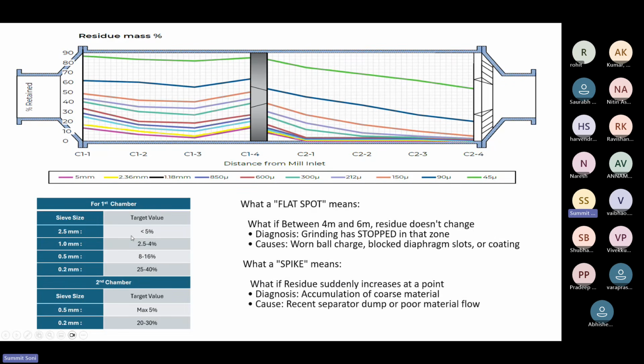For example, for the first chamber, at 2.5 mm sieve size, the value should always be less than 5%. If it is more than 5%, my grinding is not happening there. This is one thumb rule which I go with, and this is at the first chamber at the diaphragm. The location of this sample should be first chamber end at the diaphragm. We also measure for 1.0 mm and 0.2 mm. These are the values. For the second chamber, again, at 0.5 mm, it should not be more than 5%. Same location.